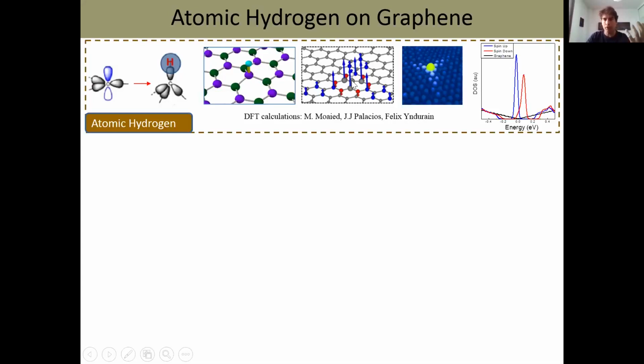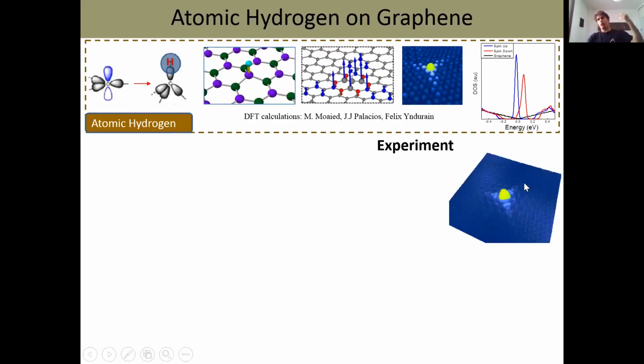And this magnetic moment that emerges has a peculiar spin texture, and according to calculations, once you adsorb hydrogen on one sublattice, a magnetic moment should develop on graphene on the opposite sublattice. This is how theory tells us that we should observe the hydrogen atom, and that's the signature of having the magnetic moment. Two peaks in the density of states, one occupied, one empty, which are the two spin components of the spin split. Okay, so now we do our experiments. We deposit atomic hydrogen at room temperature. Then we have here atomic hydrogen, and it really looks like what was predicted.